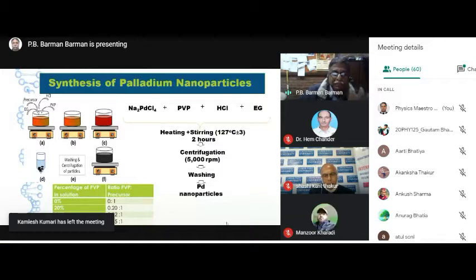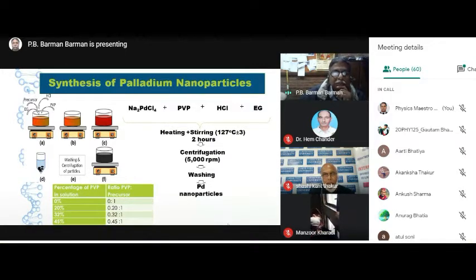So now the exact synthesis of these palladium nanoparticles is by sodium palladium tetrachloride plus PVP plus HCl, plus this is my reducing agent, ethylene glycol.